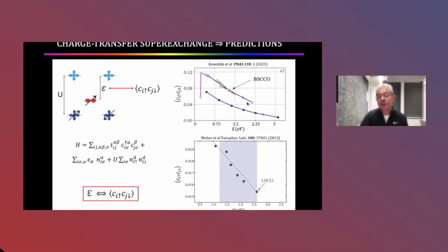And last year, André-Marie's group did this calculation for BSCCO, which is the material we can study. And they also found that the amplitude of the pair wave function evolves quickly as the charge transfer energy is increased. And of course, it evolves in the logical direction. As the charge transfer energy gets very, very large, the material has to turn into an insulator. And so the superconductivity has to disappear. And that's exactly what happens in the theories.